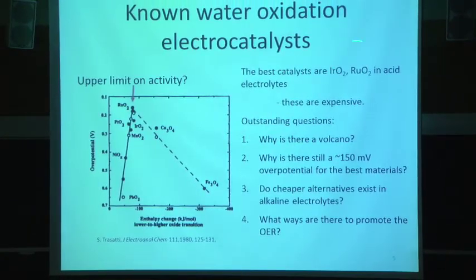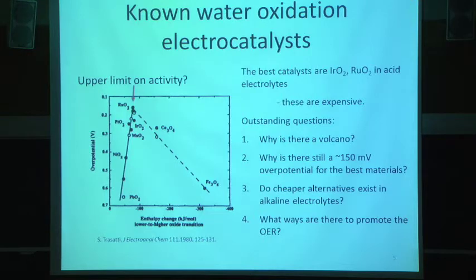And can we find cheaper metals than this in alkaline electrolytes. So once you go alkaline, you stabilize a lot of these base metals. And where iron oxide and nickel oxide readily dissolve in acid, they're fairly stable in base. Right? So can we find ways to make these better than these materials, or at least approach them so that they're cost effective? So finally, we'll talk about what kind of ways are there to promote the oxygen evolution reaction.